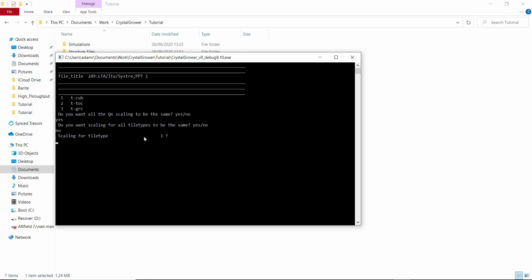If I respond with no, I then get to assign free energies of crystallization for each of the condensation steps for one of these cages. So I control them all independently. So this first step here, I'm going to give an energy cost for each missing degree of condensation from our T-cube tile. This is also called the double 4 ring in a lot of zeolite papers. Because this tile is quite small, I'm going to assign it quite a high energy penalty, so 8.0.